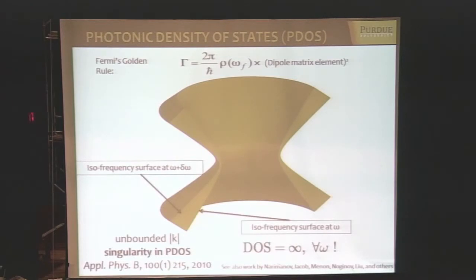So basically this means you have a very large photonic density of states, and it's not related to the conventional Purcell effect in cavities. Near resonance, you also have very large density of states, but that occurs only for a single frequency. Here, no resonance is involved, meaning you don't necessarily need large losses because it doesn't require any resonance. As long as your material remains hyperbolic - acting like a conductor in one direction and an insulator in another - you have this increased density of states. Instead of being limited by inverse wavelength cubed, here the parameter that plays a role is the thickness of the layer used to build your hyperbolic metamaterial.